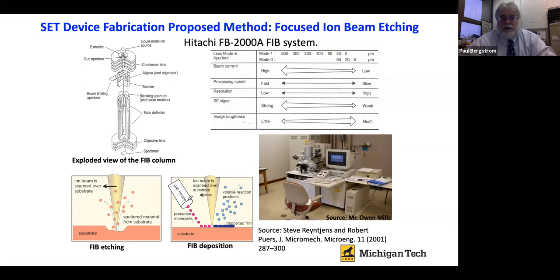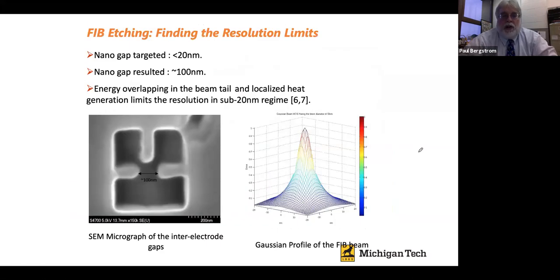You can accelerate it in an electric field if you ionize it, and so it's focused and directed to the substrate in the same way that a scanning electron microscope would use. We can control the position of these. We can control the structure. So our premise was to assume that we could build an SET based on focused ion beam etching. Our initial studies of this found that there's too much energy. The focused ion beam cannot produce small gaps and small geometries of structures given the amount of heating of the substrate that results from the beam interacting with the substrate.